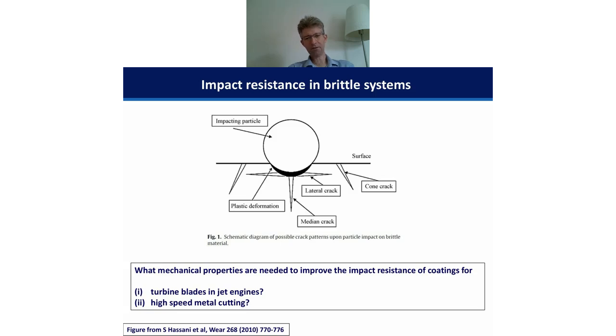So, as I said, brittle systems are typically hard, so they are used in a range of different applications, but they do have this intrinsic low toughness. Schematically, you can think about a high strain rate contact or an impact coming into a brittle material and causing a range of different deformation mechanisms, including some plasticity, but also a range of different cracking mechanisms. And that's just on a single impact. If you have multiple impacts, you can imagine these crack systems superimpose, and then you get large amounts of material removal, and this leads to erosive wear.